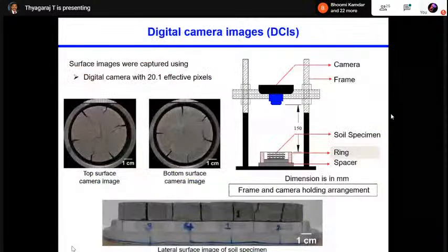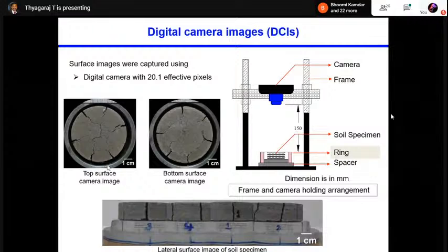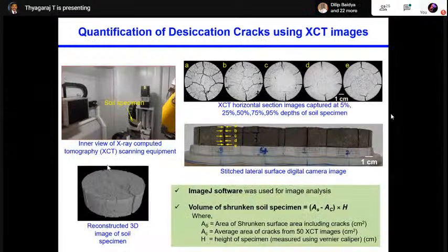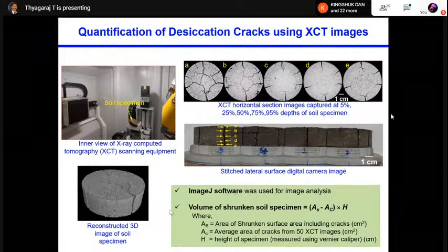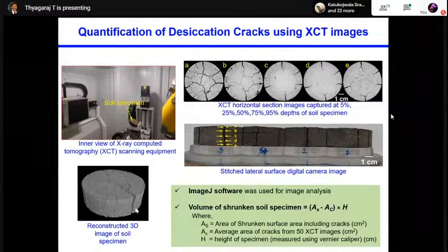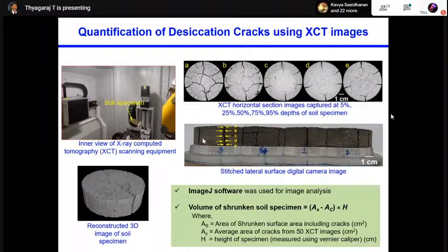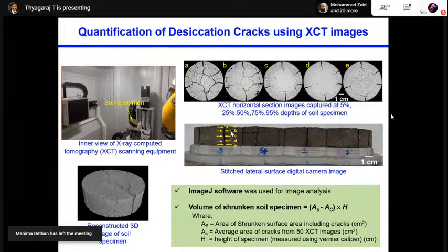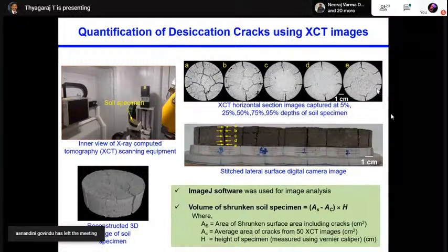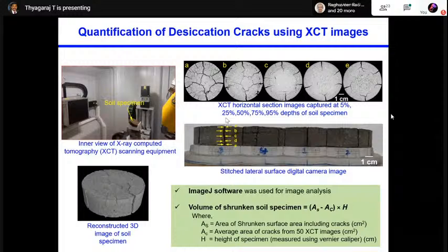So this was used just as a digital camera image, and then further we have used XCT, because this only gives the surface reading, either on top or bottom or on the circumference. In order to know what's happening inside the soil sample, we went to the XCT, the X-ray computed tomography method. This is the arrangement for that. This is a typical 3D reconstruction from the XCT machine. Here is the lateral stitched sample I have shown. At different depths, A, B, C, D, and E, we have taken the XCT images, at approximately 25% depth, 50% depth, 75% depth, and 95% depth.